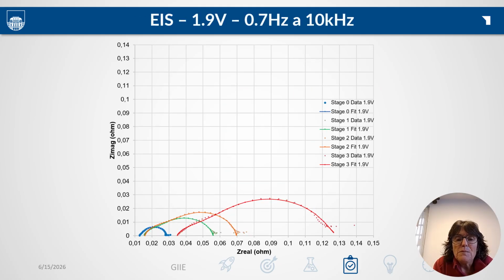This figure presents the Nyquist plots at 1.9 volts. We can clearly see the growth in the semicircles with respect to the baseline, indicating an increase in charge transfer resistance. Between the baseline and stage 3 plots, we can also clearly see an increase in ohmic resistance.